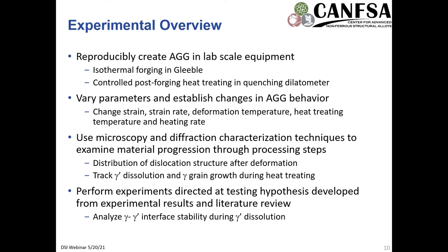And then we did quite a large design of experiments matrix through various parameters, and we varied these to establish what changes in the parameters resulted in what changes in the microstructure. That gave us some insight into possible mechanisms and how this abnormal grain growth is occurring. Additionally, at different steps after isothermal forging or after the quenched dilatometer supersolvus heat treatment, we utilized light optical microscopy, scanning and TEM, as well as diffraction techniques to examine the material processing progression throughout different processing steps.